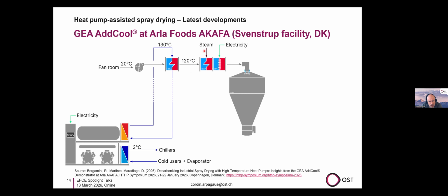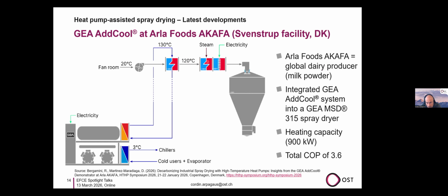So the message here is this CO2 heat pump technology manages to go up to 120 degrees. For the rest, there is still another heating technology needed. So this is at Arla Foods, integrated in a GEA MSD 315 spray dryer, so 900 kilowatt capacity, 10 times larger than the test facility shown before. And the total COP, so the coefficient of performance, is 3.6, which means with 1 kilowatt hour of electricity, 3.6 kilowatt hours of heat and cold can be produced with this system.